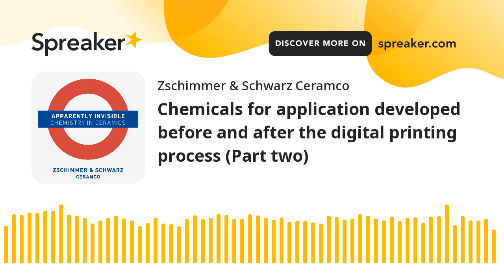Another problem that may occur in this case of a too high temperature is the evaporation of the solvent part of the ink during the discharging process. That is, of course, the liquid part within which are the colored powders. What does that mean? It means that the ink, during its fall from the nozzle to the surface of the raw tile, may partially lose its solvent part by evaporation.